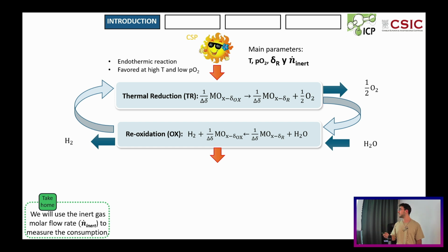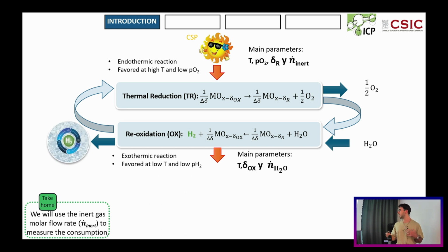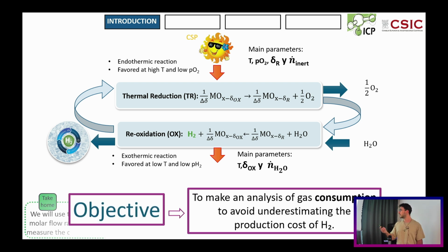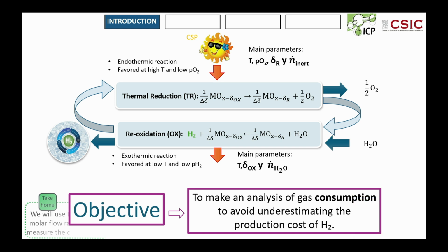Because of that, we need the use of an inert gas in order to favor the reaction to the products. The second step will be the reoxidation, when we can use the vacancies created during the thermal reduction in order to produce the hydrogen. And this is an exothermic reaction which is favored at low temperatures and low partial pressure of hydrogen. And also here we will be using a water stream which will be in excess. Because of that, our main objective here is to make an analysis of the main gases, the inert gas during the reduction and the water during the reoxidation, in order to not underestimate the production cost of the hydrogen.